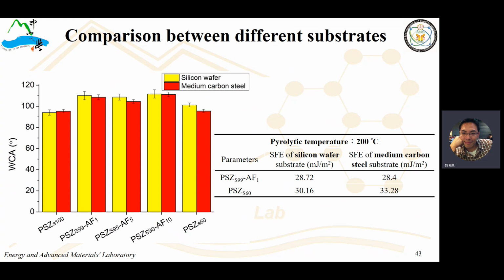We also compare with a different substrate. Previously we just spin coated this precursor, incorporating the fluorinated resin or diluted or incorporated with TiO2, onto silicon. Is it functional with a different substrate? Therefore, we compare with medium carbon steel. We use the same process, the same materials, the same compound, spin coating on the medium carbon steel, and compare with the coating on silicon wafer. It's quite similar, there's not much difference.